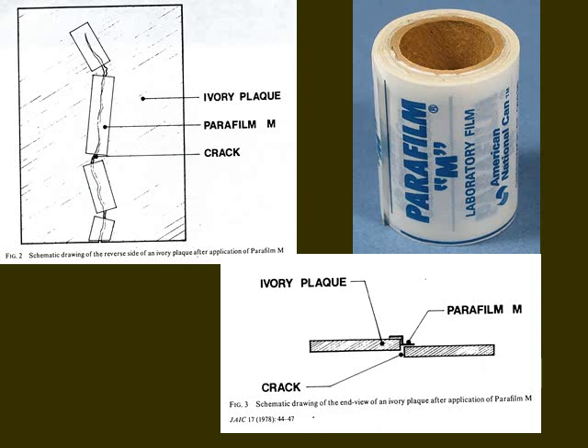Adhesives containing solvents that might leach the constituents of the ivory, or any material requiring such a solvent for its removal, could not be used. After testing a variety of materials for reinforcing the ivory, a good solution was found in an unlikely product that is normally used to seal laboratory glassware. The product was Parafilm M, a highly flexible thermoplastic film manufactured by the American Can Company. The Walters Art Museum found that Parafilm M is easily applied and removed without solvents.